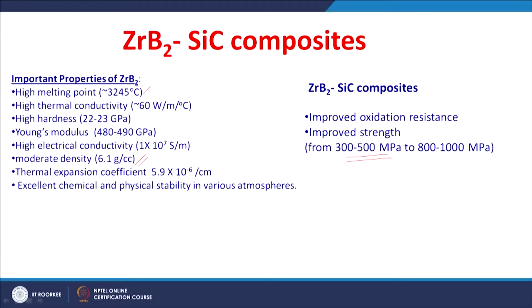And it is already reported in several studies that by adding a certain amount of silicon carbide to zirconium diboride, we can improve the oxidation resistance of these ceramics, and also we can improve the strength of this ceramic. So, for example, without silicon carbide, the zirconium diboride will have around 300 to 500 MPa strength. By adding silicon carbide, the strength may go even up to 1000 MPa.